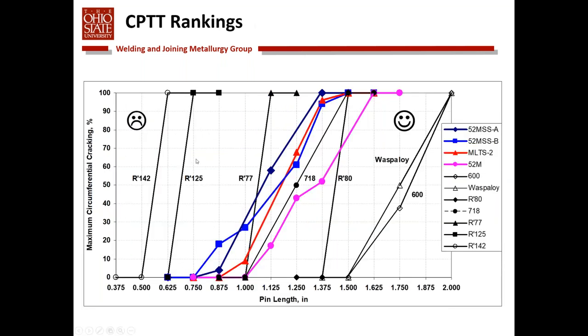Here are some Cast pin tear test rankings for some nickel-based alloys. Rene 142 and 125 are highly crack-susceptible materials. You see that they sit at the far left end of this plot. Alloy 600, Waspaloy, and some other nickel-based alloys tend to be at the far end. And so the critical pin length to cause cracking in, for example, alloy 600 is up around an inch and a half, whereas the cracking susceptibility for Rene 142 is down around a half an inch.